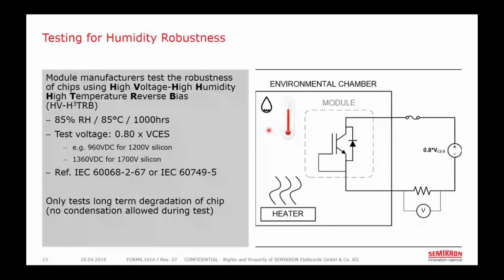Now, I want to point out that this is a very stressful test because we're forcing a high temperature and a high humidity to exist simultaneously in an environmental chamber. We just showed earlier that the relative humidity has an inverse relationship with temperature. So normally if we increase the temperature, the relative humidity should decrease. But because we're in this sealed environmental chamber, we're able to constantly hold a very high absolute humidity by feeding water into the chamber via a humidifier, as well as preventing moist air from escaping and expanding because we have this sealed chamber. In real world applications, we'll see that the relative humidity in the microenvironment inside the module will reduce as heat is applied from the chips themselves.